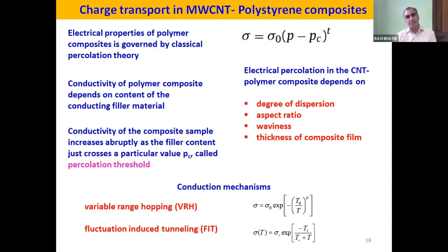Basically, two types of conduction mechanisms have been proposed to date. Variable range hopping follows the same formula which I showed you earlier, and fluctuation induced tunneling, given by Ping Sheng in 1978, follows this particular expression. Please note that both are exponential models, but here there are two other terms involved, T1 and T0, which correspond to the potential barriers to be crossed by the charge carrier to have a better transport. And in this case, T0 is called the characteristic temperature, which depends upon the density of states near the Fermi level.